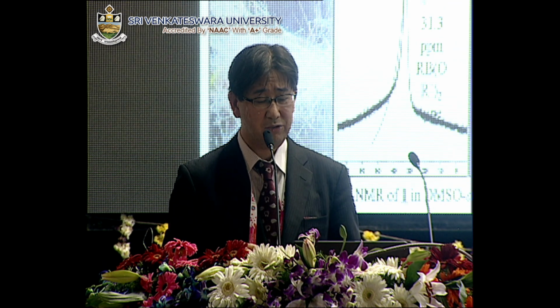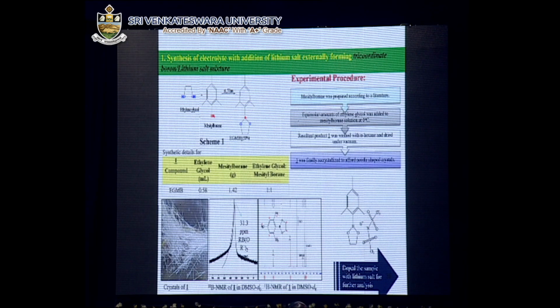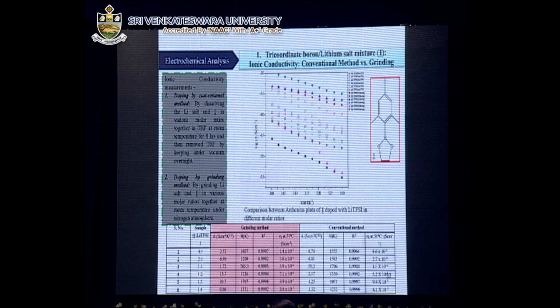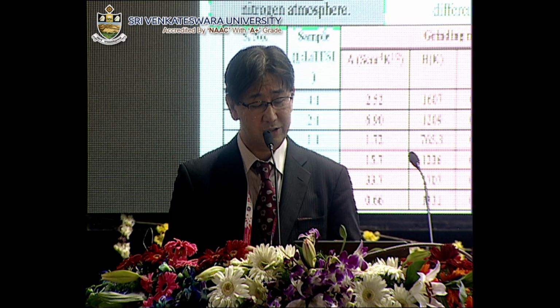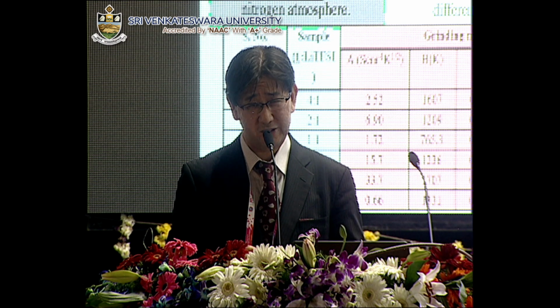The crystalline boron compound was prepared by dehydrocoupling between ethylene glycol and mesitylborane, and the resulting compound was purified by recrystallization to afford needle-shaped crystals. Their structure was confirmed by proton and boron-11 NMR spectra, and lithium salts were inserted into this compound by two different methods. The first method was doping by the conventional method, in which both the boron compound and lithium salts were dissolved in an organic solvent, and after mixing, the solvent was removed under reduced pressure.